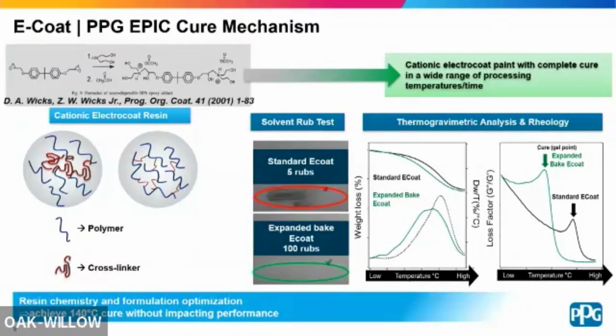So in terms of rheology, how does it flow? And we always want to make sure that we're maintaining rheology, because our customers don't like when you start messing around with that. That's basic. So how do you achieve the same rheology, but changing your bake portfolio? And here you can see on TA, you can see that your bake is staying pretty much the same, but at a lower temperature, you can achieve the gel content or the gel rating that you need. So therefore, you're curing this a lot quicker and at a lot lower temperature.